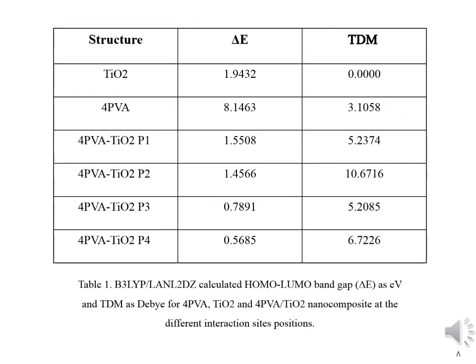The HOMO-LUMO energy decreased sharply and becomes 0.5685 electron volt for the interaction of titanium dioxide with 4 polyvinyl alcohol through the hydrogen atom linked to oxygen atom number 29 respectively. Such a strong decrease in HOMO-LUMO energy value indicates that it becomes more reactive as a result of interaction with titanium dioxide. For the same interaction position, total dipole moment of polyvinyl alcohol increased approximately to twice its value and becomes 6.7226 Debye. Also, the increase in the total dipole moment values of 4 polyvinyl alcohol upon interaction is considered as a strong indicator for the enhancement of the reactivity of 4 polyvinyl alcohol.